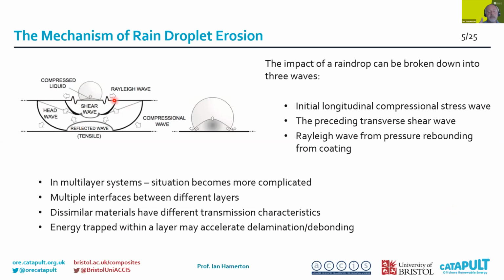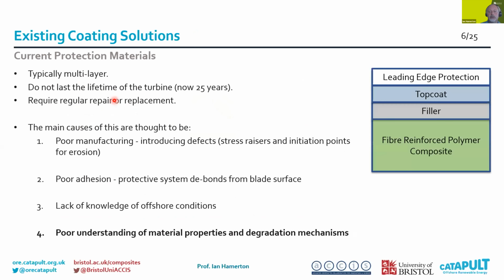a Rayleigh wave from the pressure rebounding back from the coating. So the combination of these waves causes a lot of stresses, compressional and shear stresses within the materials. And so consequently, these lead to the characteristic delamination, debonding that I showed you. And this can be a real issue, particularly when you're looking at modern current protection systems.